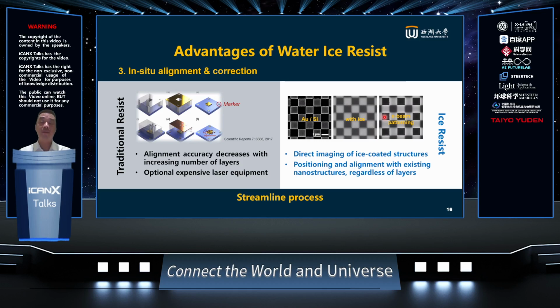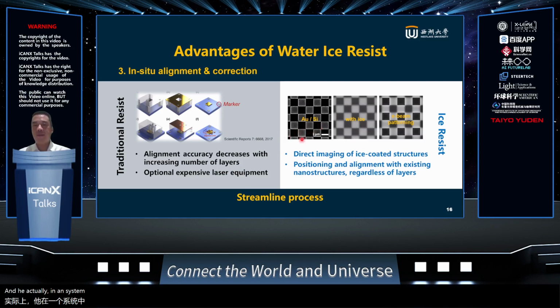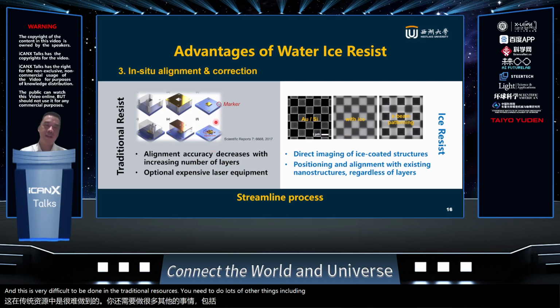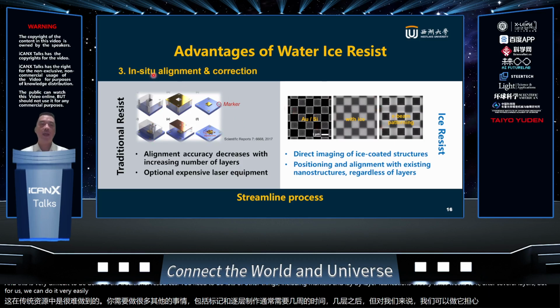And the third advantage is that we are making the water vapors directly in the vacuum, in an E-beam system. And when we make this ice, if we carefully design the structure and carefully utilize the E-beam lithography, we can look at the structure directly with ice. And afterwards, we can increase the intensity of electrons, and we start to remove part of the ice. And then we can make patterns. You can see from here, the darker part is the patterning we made by removing ice. And this is very difficult to do with traditional resists. You need to do lots of other things, including markers, and layer by layer fabrication usually takes weeks to have several layers. But for us, we can do it very easily. We can do in-situ alignment and correction.